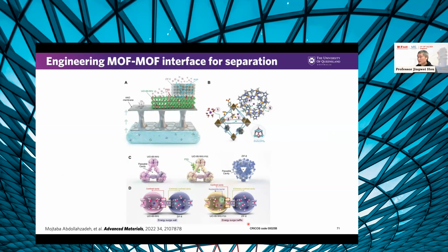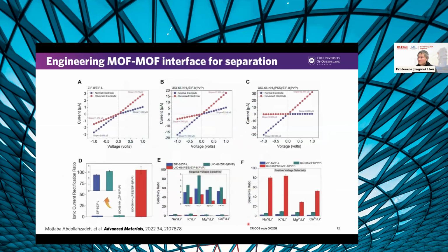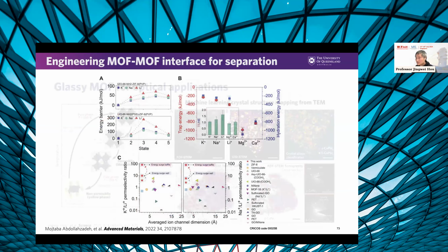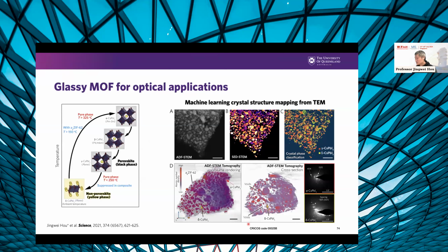This is mimicking the natural ionic channels across cellular membranes. Again, this is a kind of Janus structure, because natural cellular membranes have a Janus structure to allow highly selective ion separation. So we can make MOF membranes that are highly selective against different ions like lithium, potassium, and sodium. I probably won't go into the details given the time constraints, but that's a membrane application.